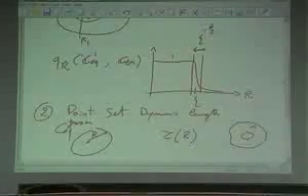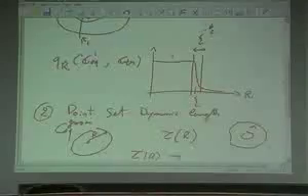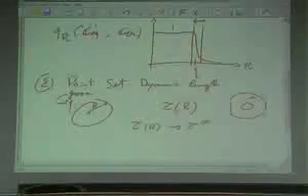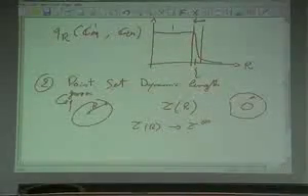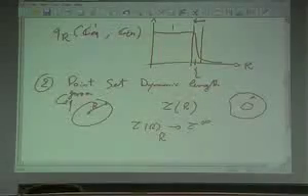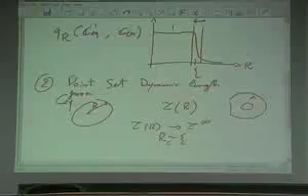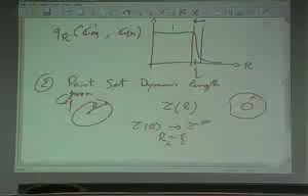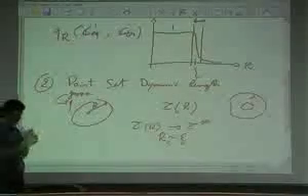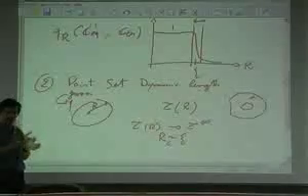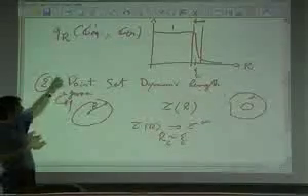And then I increase r, and increasing r, the time scale tau of r will increase. And if the whole picture is right, tau of r should go to tau for the infinite system, which is the one that you measure, I don't know, in the dynamic correlation function. And the length scale on which you have this crossover should be psi. Because, well, that's what we said: above psi, the liquid is a simple liquid. So in principle, this tells you that the mechanism that makes you relax and makes the time scale big is on the length scale psi, which is the same one that I compute here.